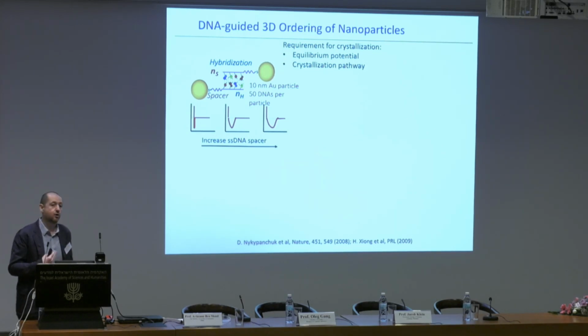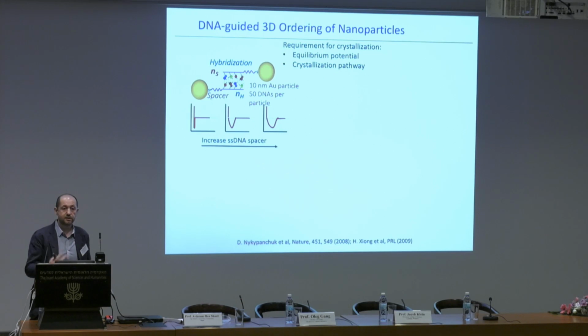There are different ways we explored to tune the interaction potential and still preserve addressability and complementarity, to take advantage of the hybridization between the particles. One of the ways which was successful is simply to use a spacer as a way to tune the repulsive interactions, where the attractive part can be tuned through the hybridization. The second aspect is really the crystallization pathway. It's not sufficient just to mix them. It's necessary to find the conditions, and this is where reversibility of interactions comes into place.